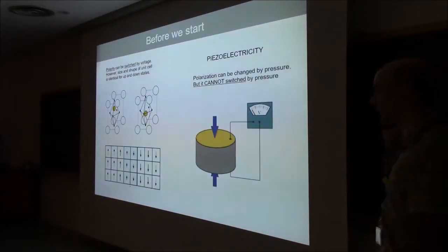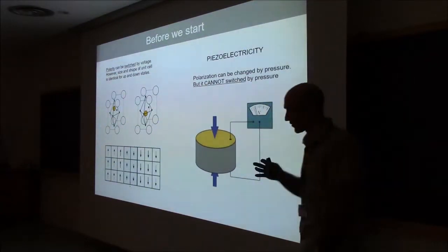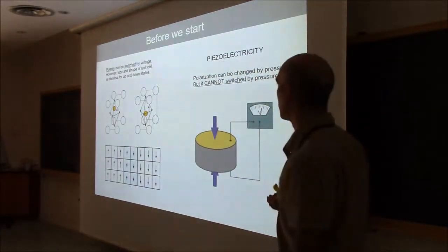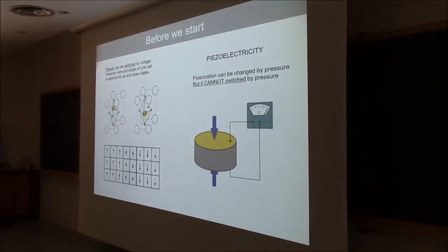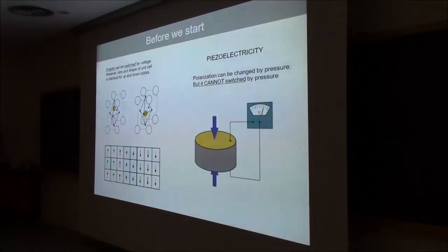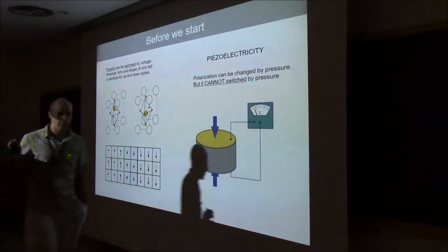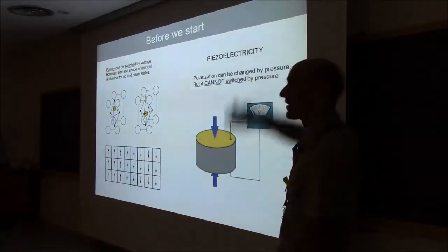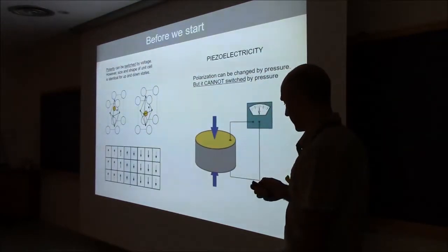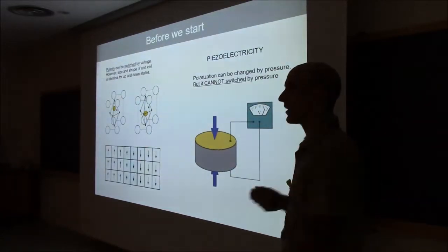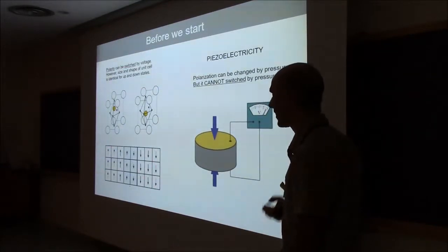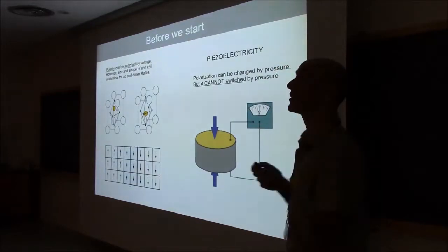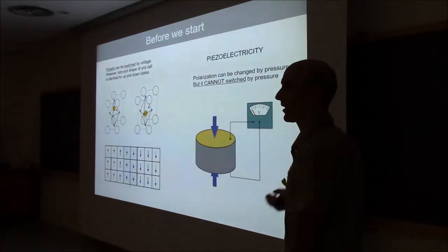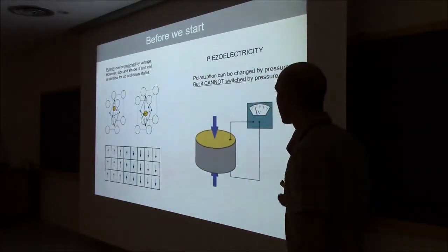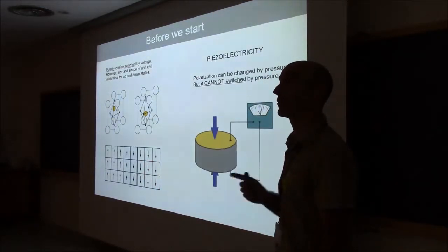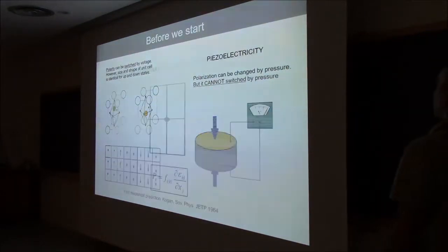Now, before I even start talking about flexoelectricity, I need to remind you of something quite important, and it will become apparent why, which has to do with the nature of ferroelectricity, and more specifically of perovskite ferroelectricity. Remember, perovskites come from a high symmetry phase that is cubic and centrosymmetric. So when they become ferroelectric, the up state and the down state have the same energy, and they have the same elastic energy. The up unit cell and the down unit cell have exactly the same shape and exactly the same size. Which means that by pressure, I cannot go from an up state to a down state, because there's no energy gain. If I apply pressure, I can change the magnitude of the polarization, but I cannot change the sign of the polarization. That's quite important. Okay, that's before we start, now we start.